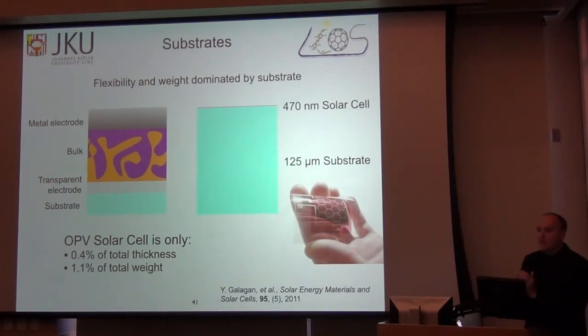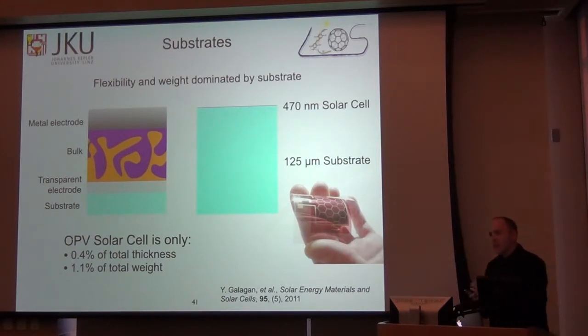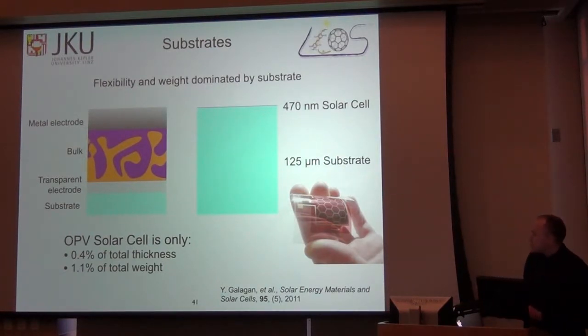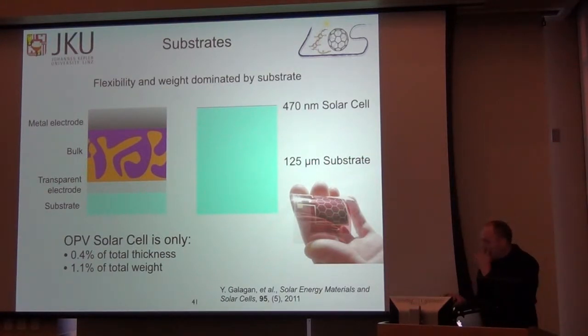Some significant improvements in terms of the weight and flexibility of these devices. One of the biggest advantages, or the most often claimed advantages of organic photovoltaics, is that they are thin films, and so they are lightweight and flexible. But I showed you this picture here several times before, but even for this flexible organic solar cell, which is from the ECN in the Netherlands, if I draw this picture to scale, everything is the substrate. Everything interesting and electronically active is contained in this purple thin line at the top. The solar cell itself consists of roughly 1% or less of the total thickness and of the total weight of the solar cell.